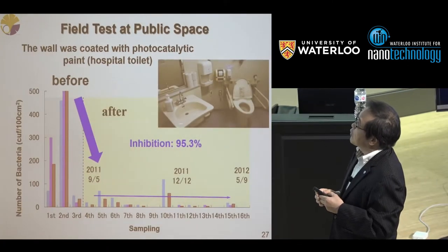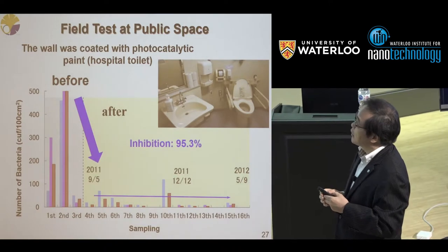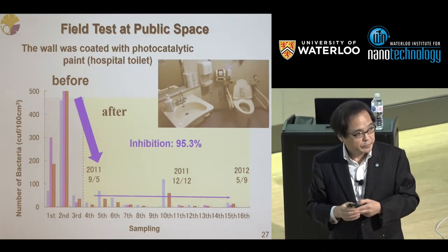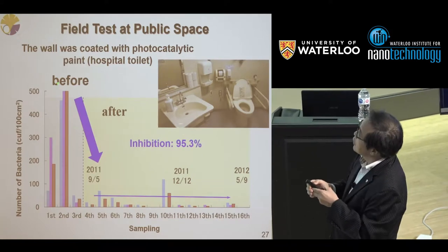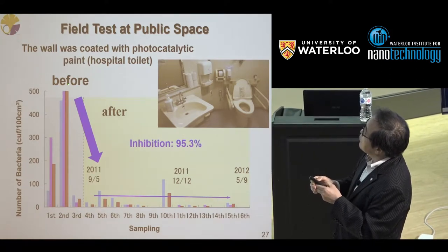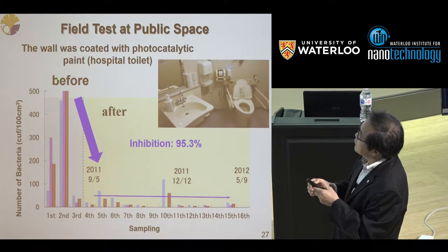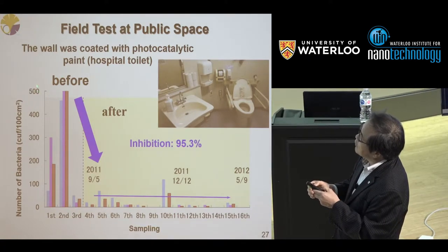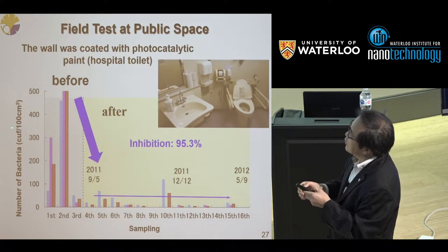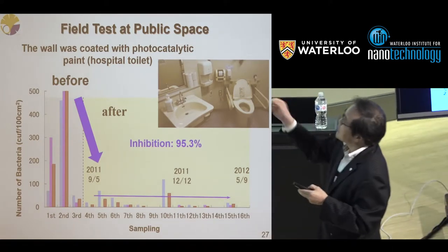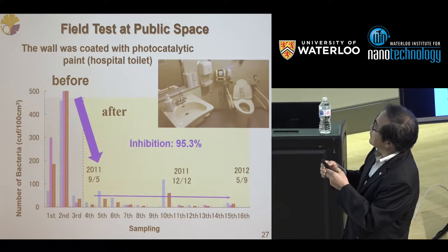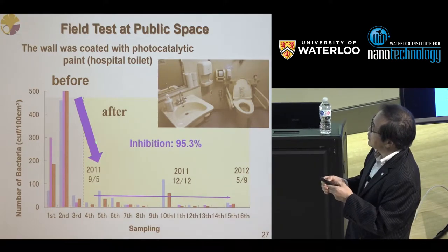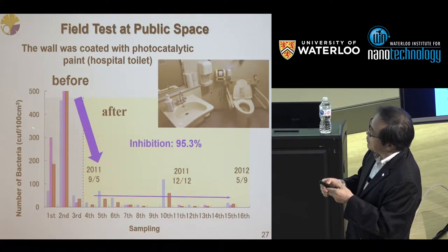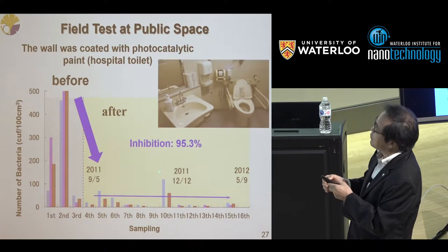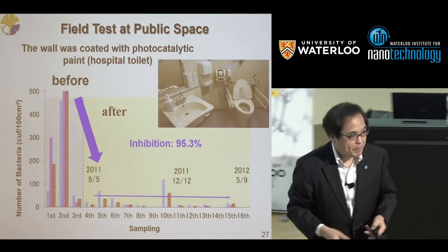This is a field test at a public space, actually in hospital toilets, bathrooms. Before using our coating system, they had about 500 bacteria, the number of bacteria in 100 square centimeters or something like that. But after coating the walls with our newly developed catalytic paint, the number of bacteria drastically decreased like that. Inhibition ratio is more than 95%.